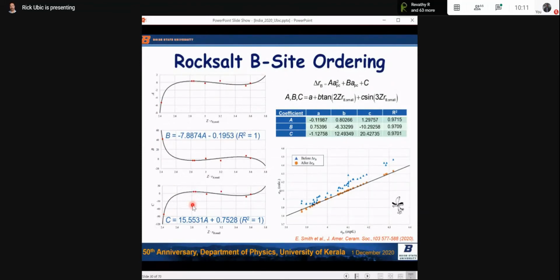They're not independent. B is a function of A, C is also a function of A, and therefore B. So we can simplify things a little bit, and we get the ABC coefficients have this sort of form. This describes these curves. And for little ABC, you stuff in these coefficients here. So we can calculate ABC, which means we can calculate the rest of it. And when we do that, we have the result down here. The blue data points are without accounting for the B-site ordering. The orange data points are where we account for the contraction caused by the order. So that works. I'm going to move along.